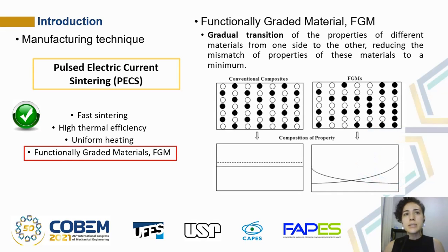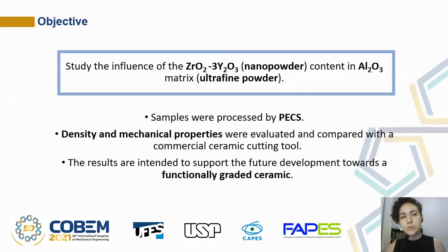FGM is a kind of composite that promotes a gradual transition of the properties of different materials from one side to the other, reducing the mismatch of the properties of this material to a minimum. So, the objective of the study is to study the influence of zirconia stabilized with yttria content in alumina matrix. The samples were processed by PECS.